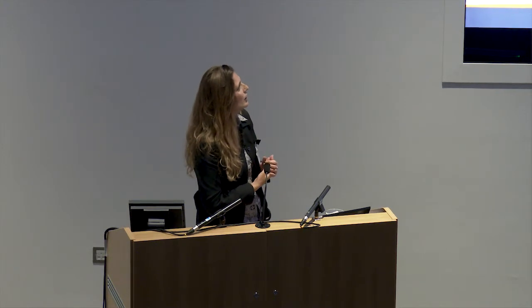The main deviations are between the two legs, the above side of the part. The legs are moving like this. We have found some deviations on each of the four specimens, sometimes from only 0.1 millimeter, but from one of them till 0.6 millimeter, so that's not nothing. And this is a kind of surprise, and for now we cannot really explain, especially because we had also performed in the project some residual stress analysis,